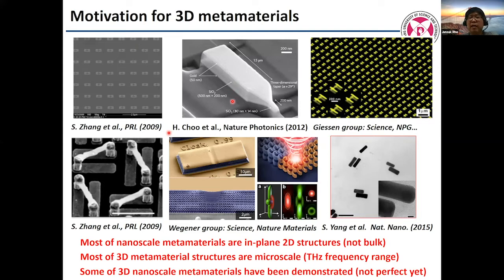Using FIB, e-beam lithography, direct laser writing, and chemistry, they all have pros and cons. FIB can make very sophisticated structures, but very few people can do that. Direct laser writing is 3D printing. This is very good, but we need electroplating, and it is somewhat limited in terms of design. So our approach is using e-beam lithography, just doing overlay, and then I realized this is also not easy, so we cannot achieve visible. So we use chemistry, making much smaller chiral structures.